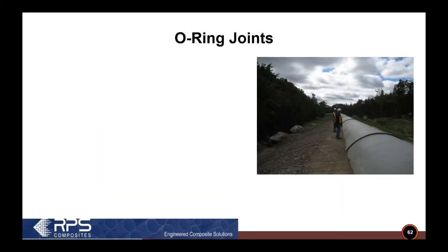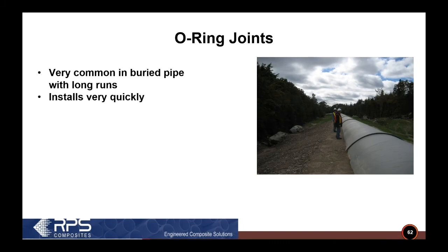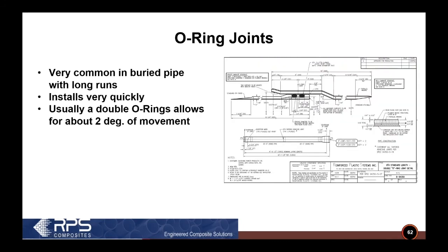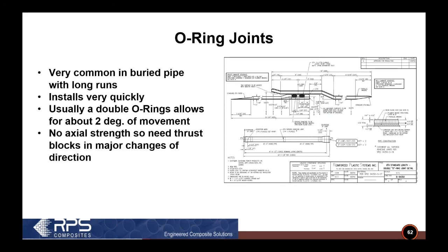And I won't go into O-ring joints. They're usually reserved for cooling water pipe, large diameter pipe, but they certainly work. You can basically install the piping very quickly using a double O-ring system. This particular system doesn't have axial restraints, so you'd need to have concrete thrust blocks where you had major changes in direction, but it definitely does go quickly and works well.